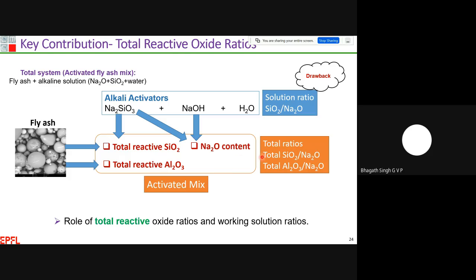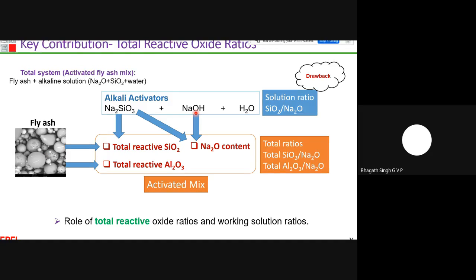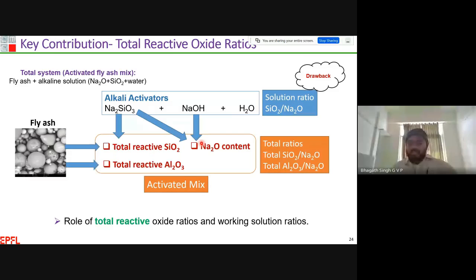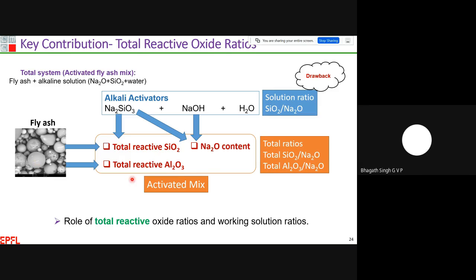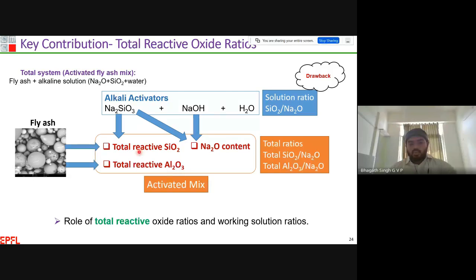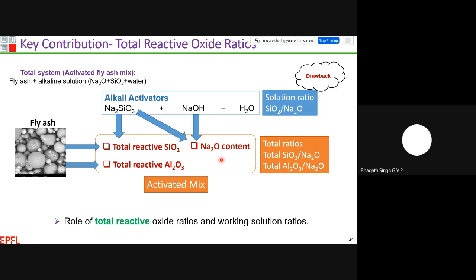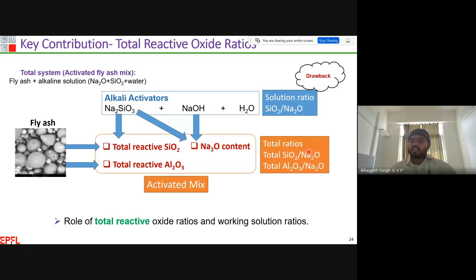The total reactive oxide ratios I have determined based upon the total reactive oxide contents present in the activated mix. The activated mix is nothing but the fly ash, which contributes the reactive silica as well as reactive alumina to the system, and the sodium silicate as well as sodium hydroxide, which contribute silica as well as sodium to the activated system. If the fly ash has alkalis like potassium or sodium, those alkalis also we have to consider while calculating these ratios. And this is the total reactive oxide content present in the activated mix. Based on these contents, I have determined the total silica to sodium ratio as well as the total alumina to sodium ratio in the activated mixes.